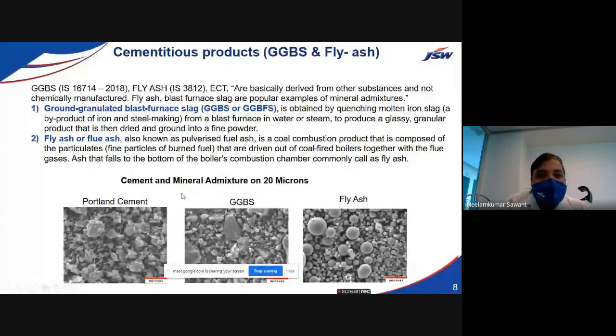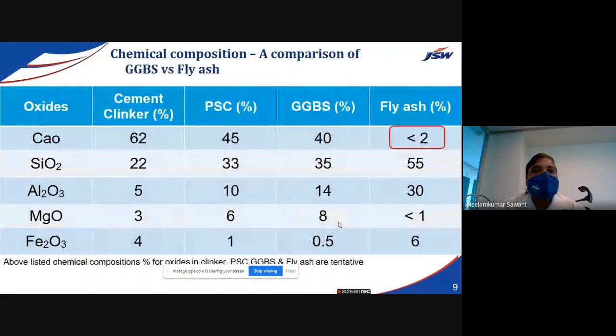So you can see on the bottom side one of the Portland cement, OPC, the microscopic picture is there, then the GGBS in the center, and the fly ash is spherical or like that sizes we are observing. So these are the particle size distributions of GGBS, Portland cement as well as fly ash particles. We will see the GGBS versus fly ash comparison.